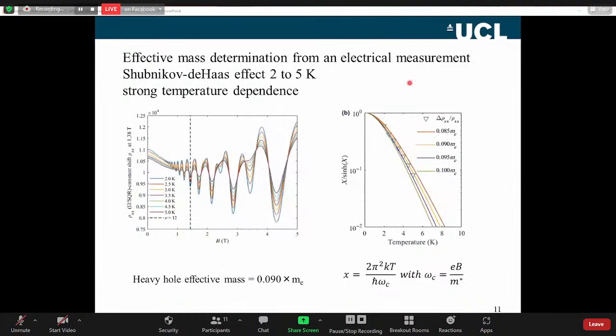Okay, so what happens when we cool this device down? So we make something called a Hall bar. We put contacts on there which are platinum. We anneal the platinum into the device. Contacts on. We cool the device down. We saw these very, very clear quantum oscillations due to the magnetic field. So the y-axis here is resistivity, passing a small current, measuring the voltage drop along the Hall bar. We measure that as a function of magnetic field. Blue line is the 2 Kelvin. This data was taken in the LCN at UCL. Very nice system for doing this.